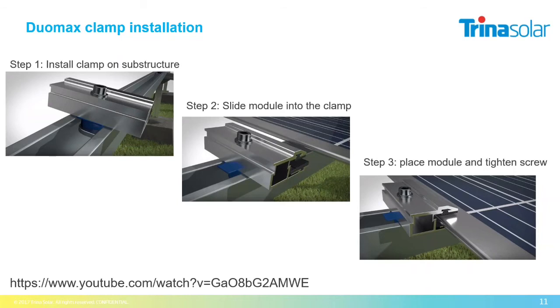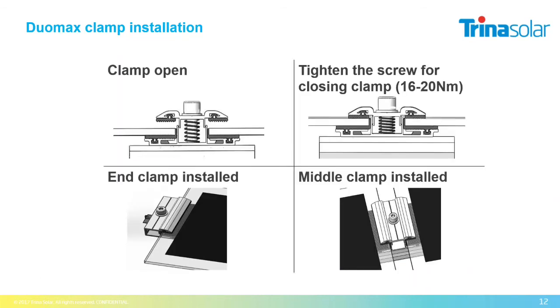With clamps, you usually need a person who is holding the module, since the module can slide down until the clamp is closed. What is also important here is that in the first steps, that means step 1 and 2, the clamp is open, and then you put in the module, and then you have to tighten the screw with a certain torque. In our case, it's 16 to 20 Newton meters, but this also depends on the clamp. For glass modules, it's very important to have the screws tightened with a certain torque, since a too low torque means the module can slide down, because you need a minimum pressure onto the polymer and then onto the module, so that the module is not sliding down or slipping out.